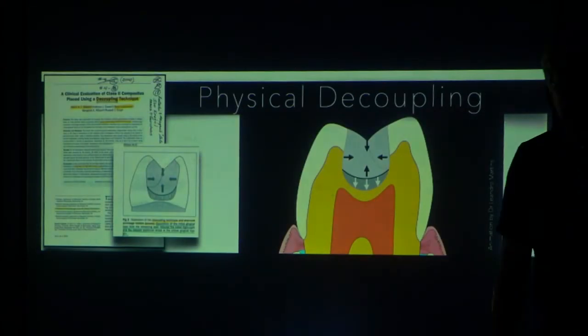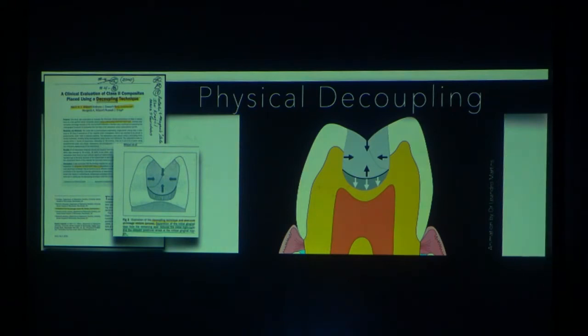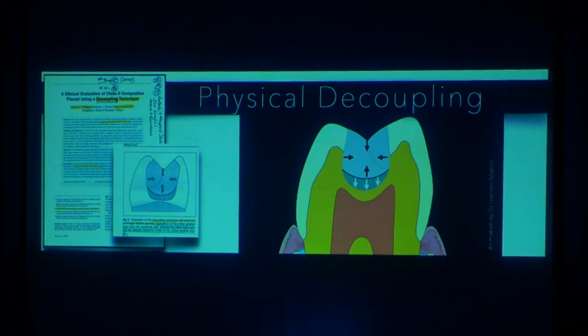And then finally, an idea came that actually worked. There was no sensitivity in these restorations in England that were pioneered by Naren Wilson and Gary Unterbrink and their team from Ivoclar if they made a layer between the 1 millimeter of composite. So they would put 1 millimeter of composite close to the pulp as kind of a liner. And then the bulk on top of this was in two increments, but this black line right here was an unbondable material, kind of like Vaseline. In other words, it totally separated the 1 millimeter on the bottom from the 3 or 4 or 5 millimeters on the top. When they did that, the sensitivity on the restoration disappeared. And they called this a decoupling technique.